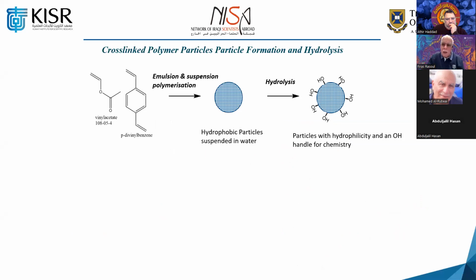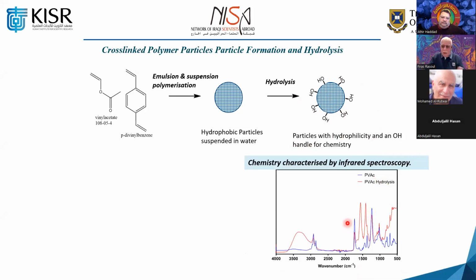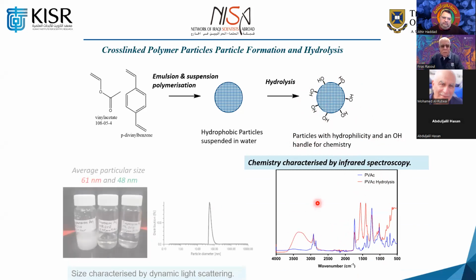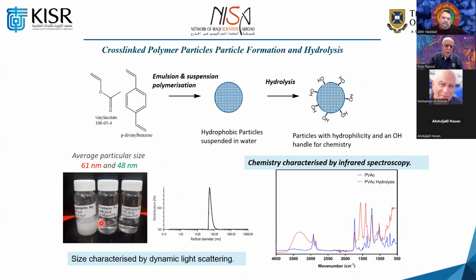suspension polymerization nanoparticles, which, as I said, are from vinyl acetate with divinyl benzene. You copolymerize it using emulsion and suspension polymerization techniques. You produce this hydrophobic particle suspended in water. Then you hydrolyze it. You hydrolyze the acetate to convert it to an OH, which is basically an alcohol, and you will be able to use that. Again, we characterize it before hydrolysis and after hydrolysis to make sure the hydrolysis is happening. And of course, here is showing you the suspension and the average particle size.